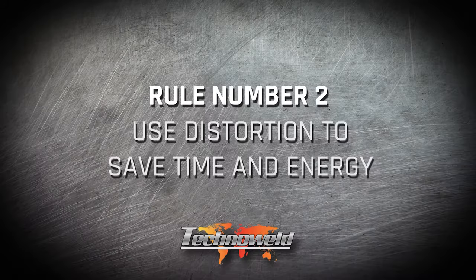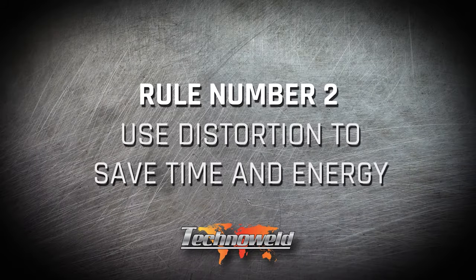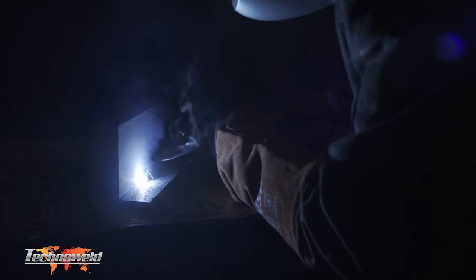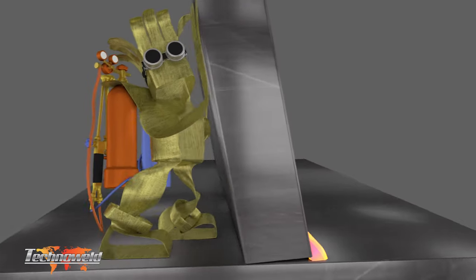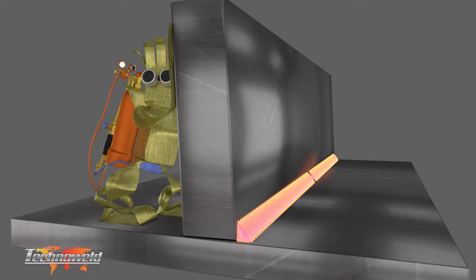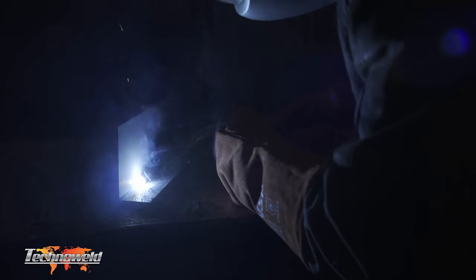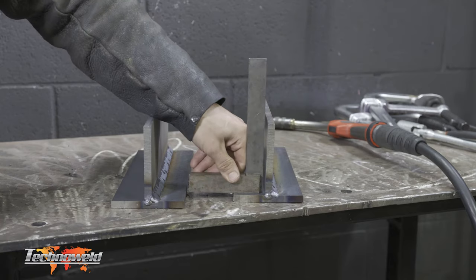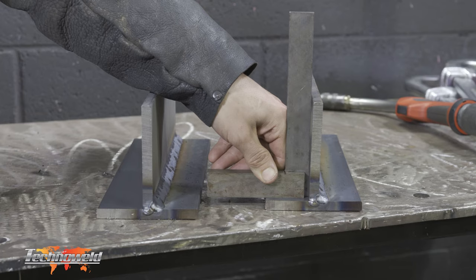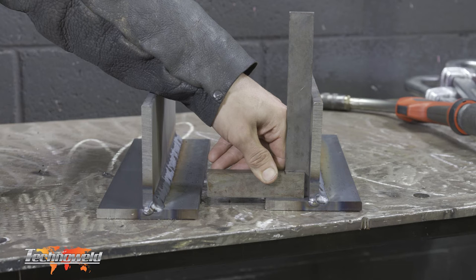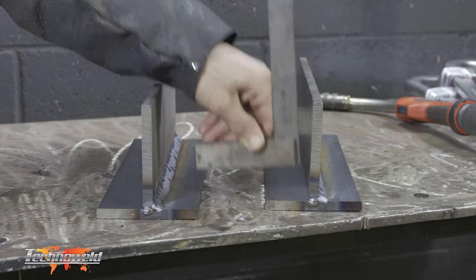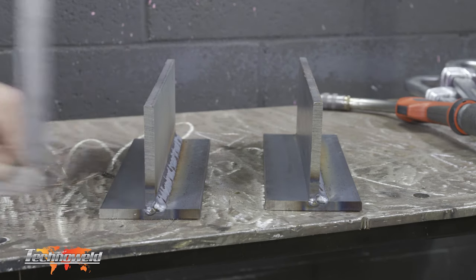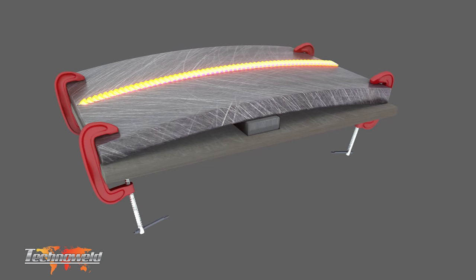Rule number two: use distortion to your advantage. If we know how much shrinkage distortion will create, we can take advantage of this by presetting our material. We see Flexi getting to work and pushing the vertical metal straight as shrinkage occurs. As the weld cools it contracts and pulls the vertical plate into alignment. As we can see here, the right hand weld was not preset prior to the weld and created a joint which is not square due to distortion. The vertical plate is not 90 degrees to the horizontal plate. By predicting the shrinkage force, the left side example was preset before the weld and resulted in a square weldment.